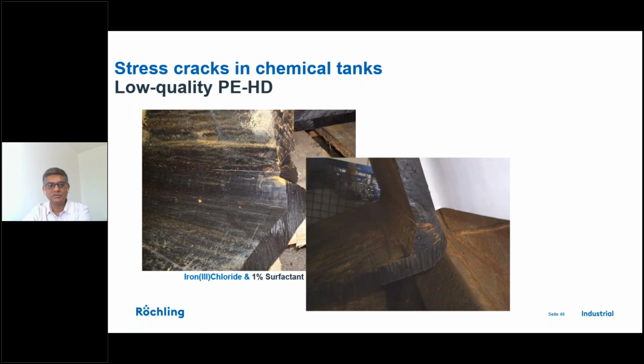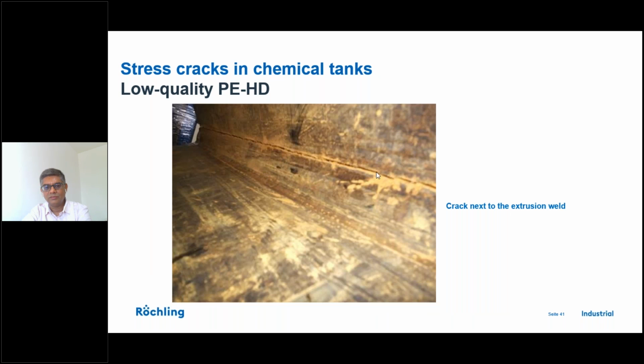These are some of the pictures of how stress cracks develop in a chemical tank made with low quality HDPE sheets. You can see basically near the weld joints, you will always see the cracks. And this is what is avoided in our material when you use good quality HDPE sheets and the right welding rods.